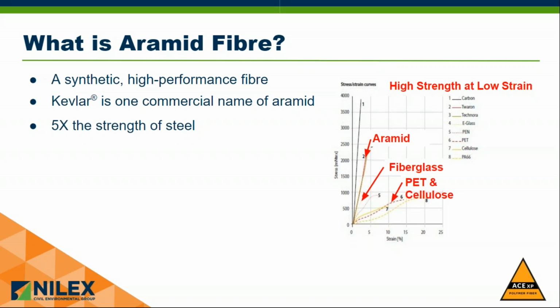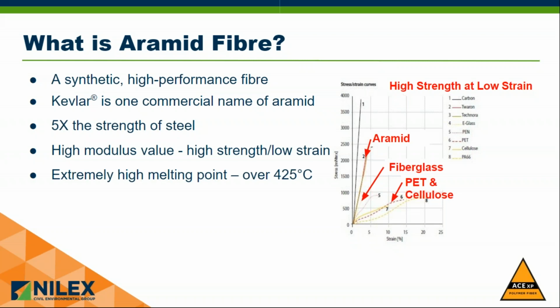The fiber itself has 5 times the tensile strength of steel. But because it has a very low strain, it means that it's a high modulus material, which makes it very effective at reinforcing asphalt pavements. Aside from the tensile strength, one of the biggest factors that helps aramid work within an asphalt pavement is that it's got an extremely high melting temperature. The melting temperature at 425 degrees is well in excess of the typical temperature ranges in which we're making asphalt pavements. So there is no possibility of the fiber melting during the mixing process. So that combination of high strength, low strain, and temperature sensitivity of the material makes it a very effective reinforcement for asphalt pavements.